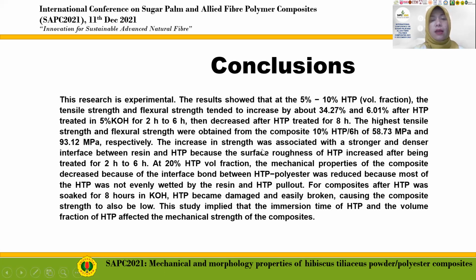The increase in strength was associated with a stronger and denser interface between resin and powder because the surface roughness of the powder increased after being treated for 2 hours to 6 hours. At 20% powder volume fraction, the mechanical properties of the composite decrease because the interface bond between powder and polyester was reduced, as the powder was not evenly wetted by the resin and powder pull out occurred.